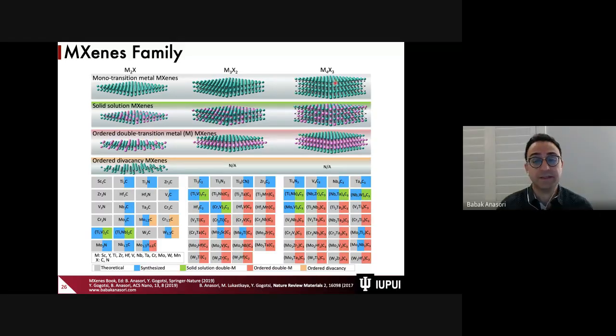Now, in MXenes, we can have 2, 3, or 4 layers of, for example, titanium and carbide. So here it is Ti3C2, titanium and carbon. We can go one step further and use 2 different metals, for example, titanium and molybdenum, or titanium and vanadium. If you use titanium and vanadium, what we get is what we expect, which is alloys, a solid solution composition where we mix 2 elements like titanium and vanadium, and they form these mixed structures.